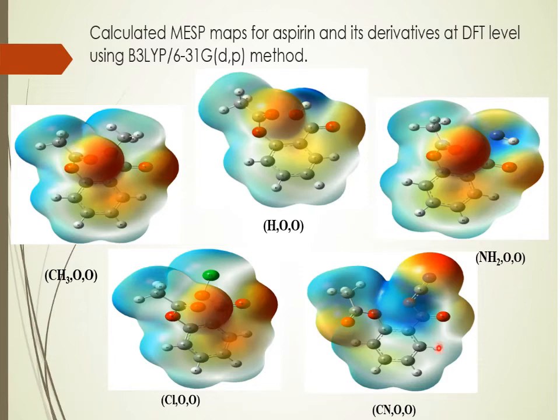For the cyanide, it creates a blue region around the oxygen of the carboxyl group and the oxygen in position X2. Also, a dark red region appears around the nitrogen atom due to high electronegativity. In NH2, it impacts the redness of the benzene ring, and NH2 itself has blue and yellow colors.